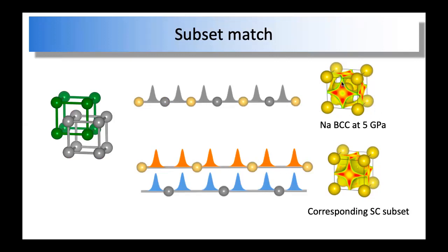Okay, and if you calculate the ELF, the electron localization happens at these tetrahedral sites, the maximum, right? So if we assume this whole lattice, both yellow and black balls, are the BCC lattice atoms, then the localization happens at these sites, and assuming these sites are the tetrahedral centers, they form the tetrahedral sites, right? Now, if you split this into two sublattices and then recalculate the electron localization.